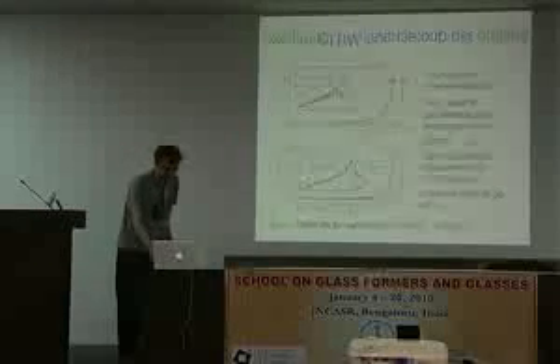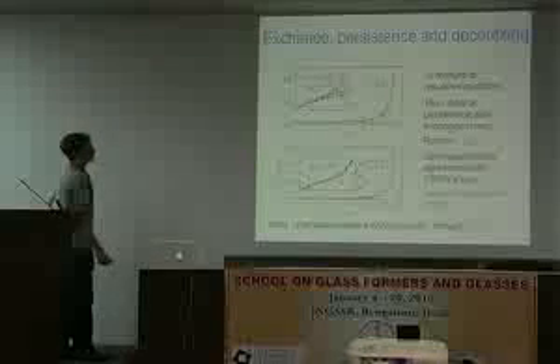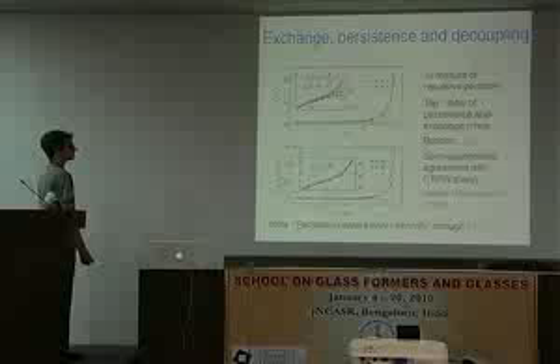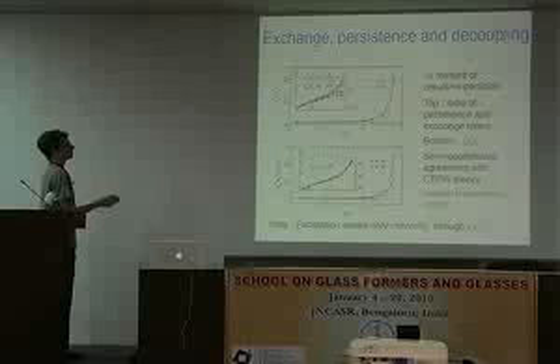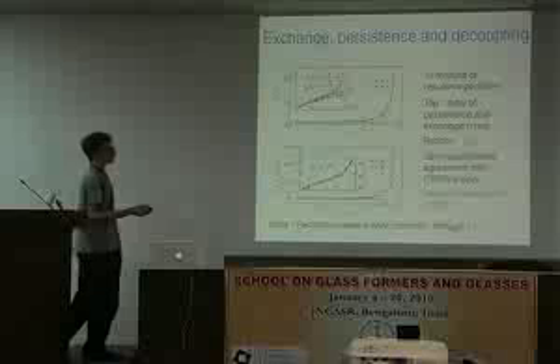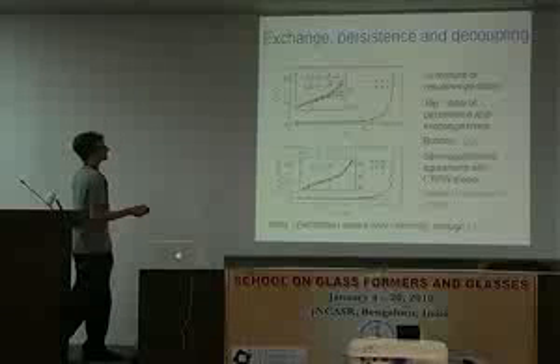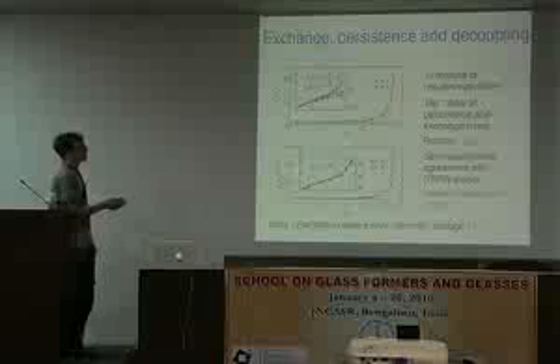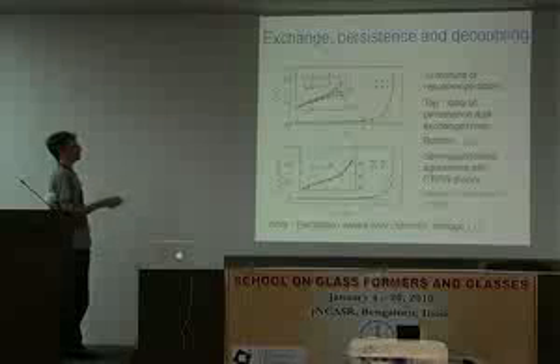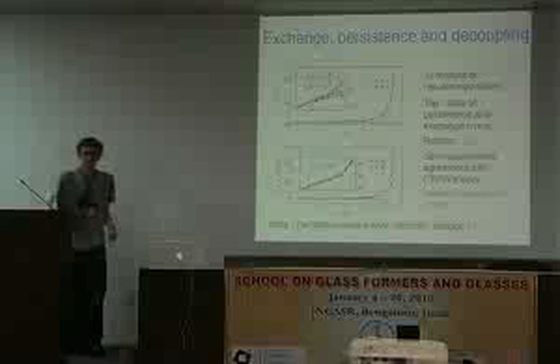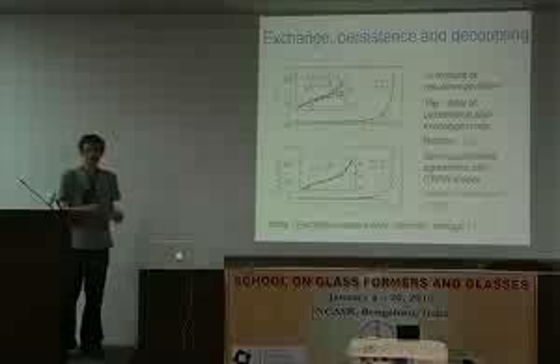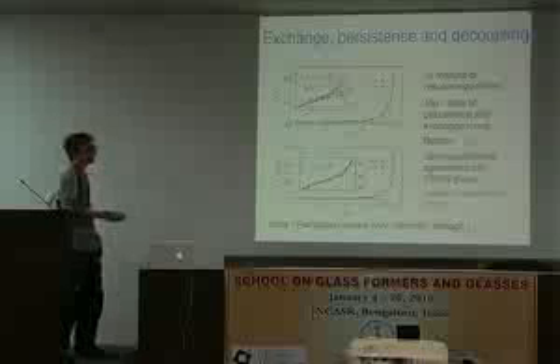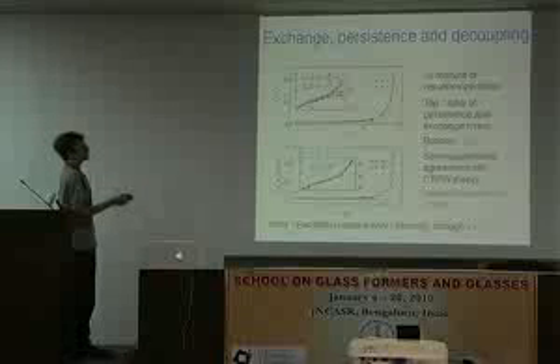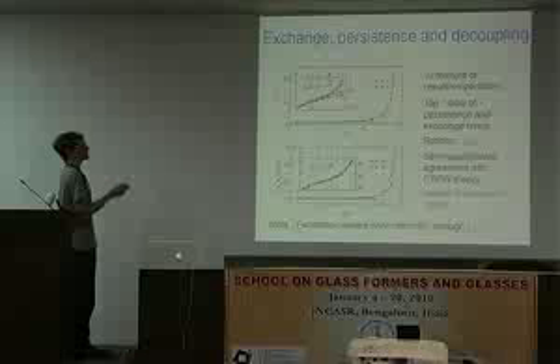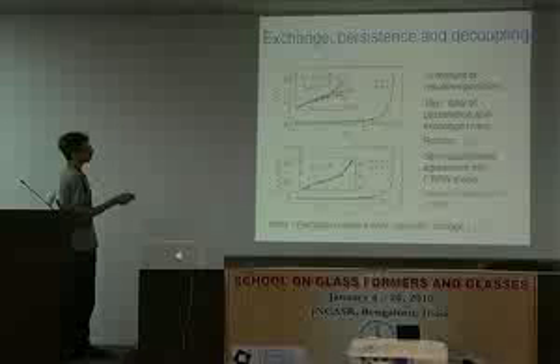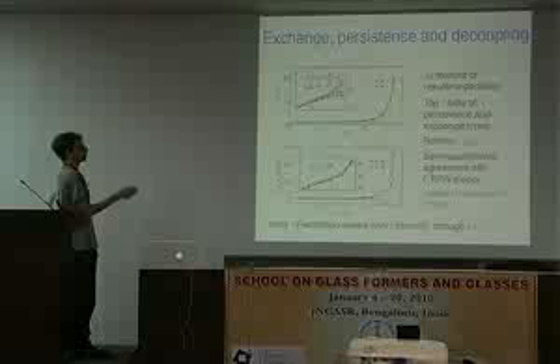So what about real liquids? So here's some data for real liquids. This is all quite busy, so I guess I should talk you through it. So it's a two-dimensional mixture of repulsive particles, he said. I think it's two-dimensional. It's a WCA mixture anyway. It's repulsive particles. And this top figure shows the ratio of the persistence and the exchange time. So we're not on a lattice anymore, so it's not obvious quite how to define that. But you define it by saying once they've moved a certain distance, that's judged to be a hop. And you can see that as you decrease the temperature, there's this strong increase in the ratio of persistence to exchange that starts to take off at about the onset temperature and gets actually pretty big for this model.